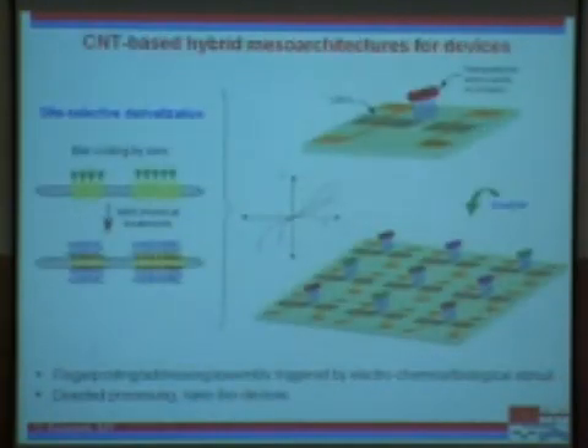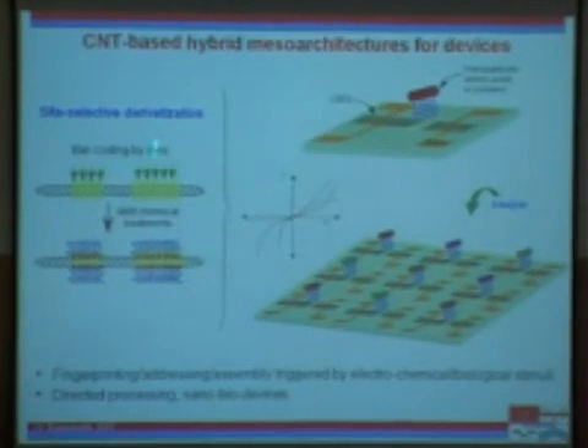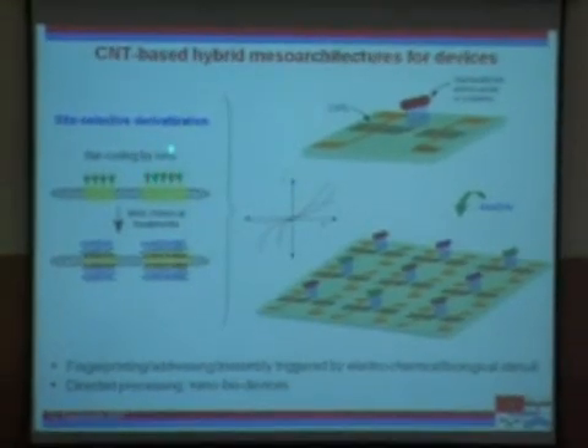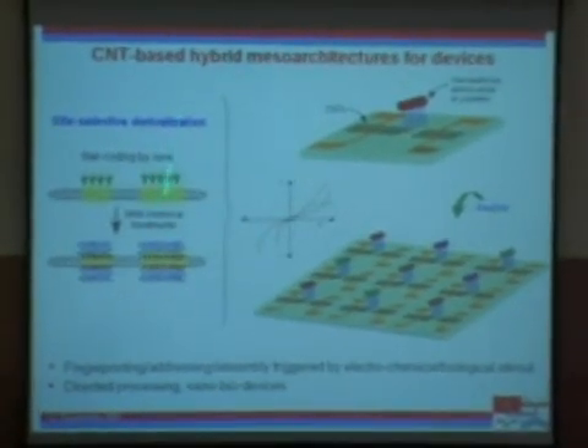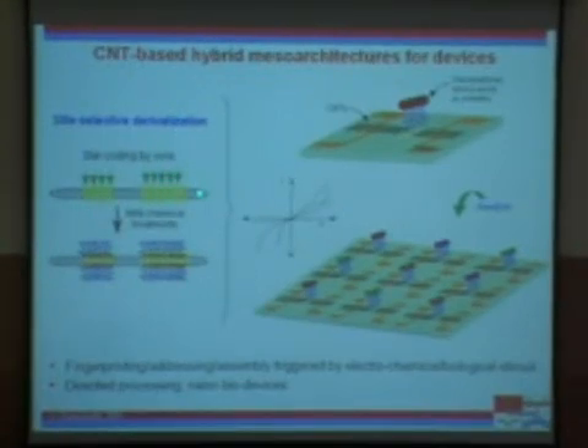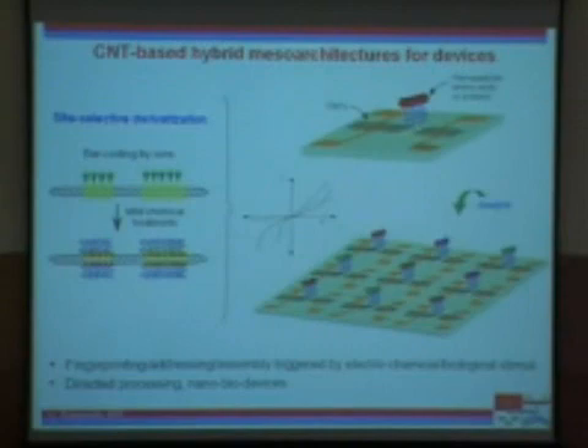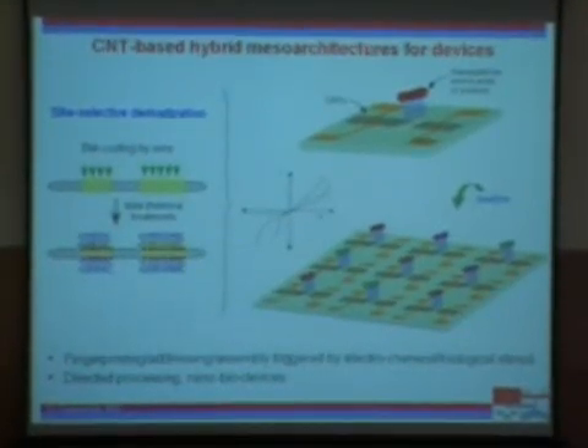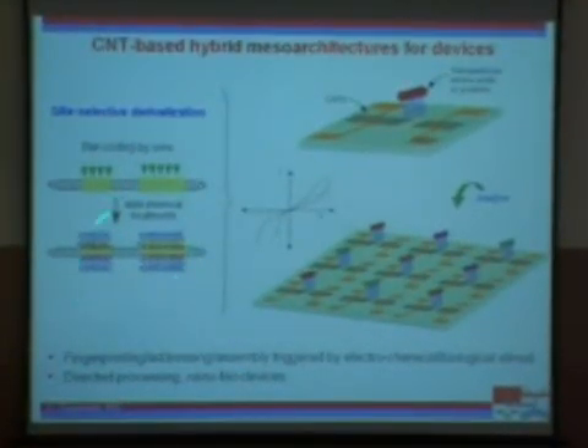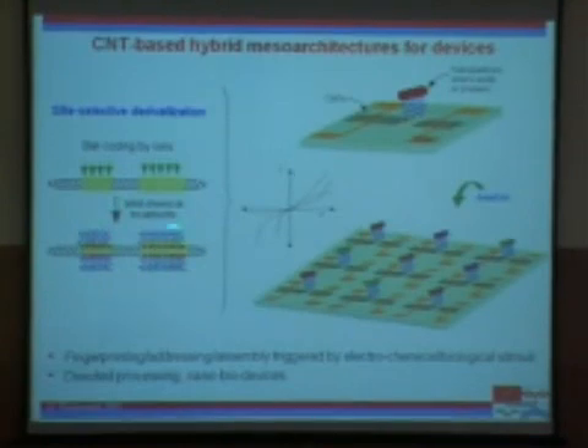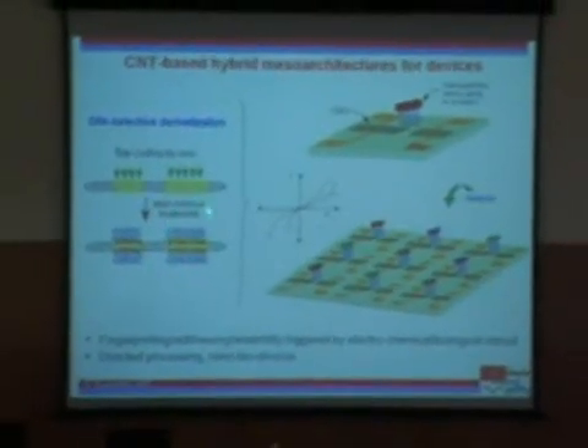So we explored a few different approaches. One of them is by using kilo-electron-volt ions. You use them to actually break bonds. You not only get spatial resolution by controlling the size of the ion beam, but also you can do this in a controllable fashion in terms of how much damage you create, as opposed to destroying the tube, which can happen when you put it in an acid. And after that, you can use mild chemical treatments to then attach molecules or other structures.